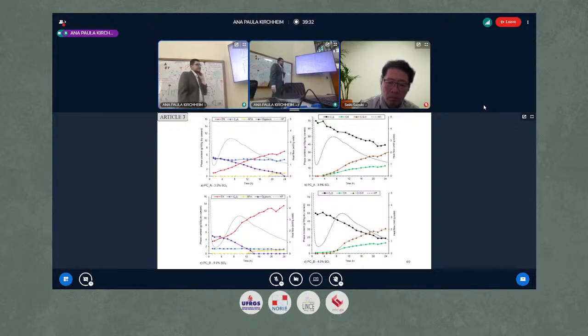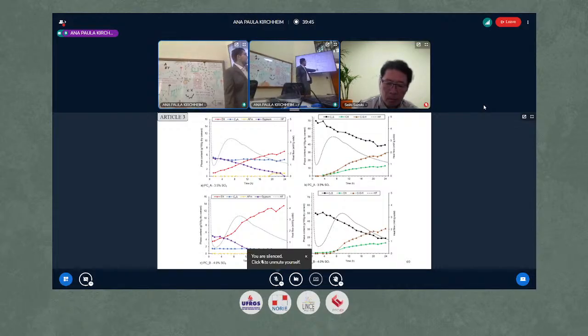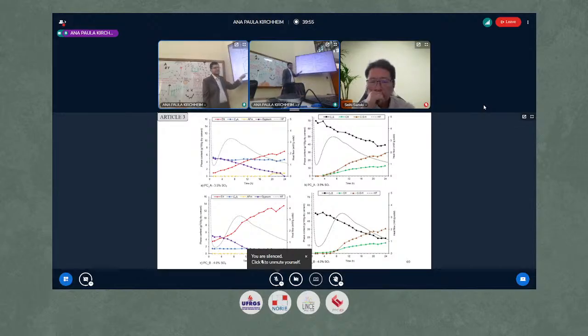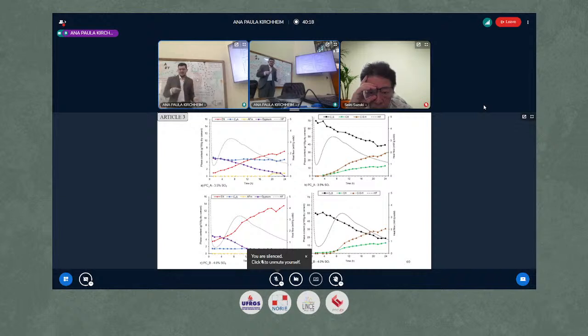And we ran an in situ XRD analysis in all of the optimized mixes. Due to the time, I will not show every one of them, but here we see the similar behavior. Alite is consumed constantly up to the end of the period when we start to dissolve and form CSH and portlandite. And in terms of aluminate, we have our initial solution of C3A, then C3A keeps the same for the first 24 hours, while it's forming ettringite, dissolving gypsum, until the moment that not enough gypsum is in the system, and we start to form AFm phases.